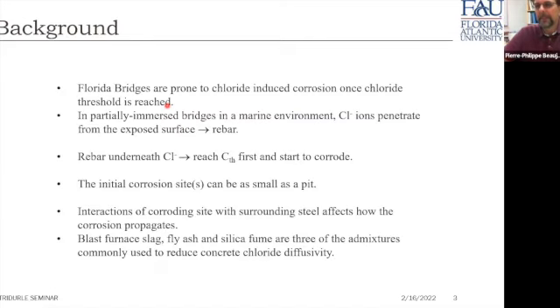Now, in terms of what is physically happening, Florida bridges are prone to chloride-induced corrosion once the chloride threshold is reached. In a partially immersed situation, such as the piling of bridges in the marine environment, the chloride ions are going to penetrate from the exposed surface into the rebar. The rebar underneath is going to start to corrode once a critical level of concentration is reached in and around the rebar. For the detail on this, I would send you to the presentation by my colleague, Dr. Preswell, who presented a couple of months ago, and his presentation should be on the FAU website. I am personally an acoustician, not a chemist, and as a result, I do not go into a whole lot of detail on this process.